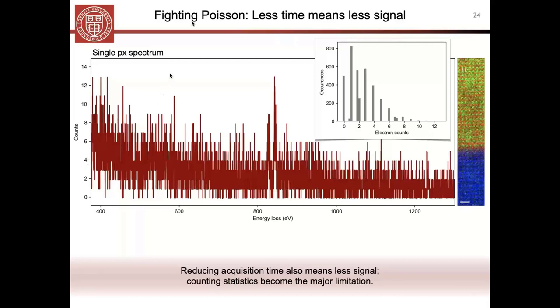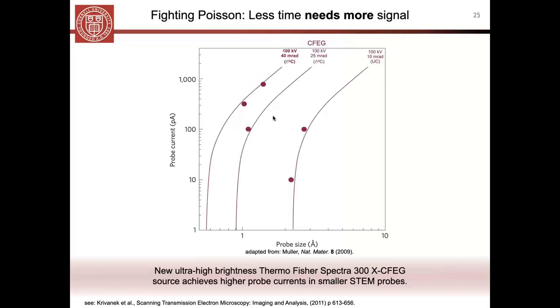And so really what this means is, having outrun the drift of the holders by moving to these fast, low noise detectors, what we're really up against now is just the statistics of the experiment. And so what we want to do to increase the signal without increasing the time, the way that you can do that is by actually just increasing the number of electrons that you put through your sample, right?